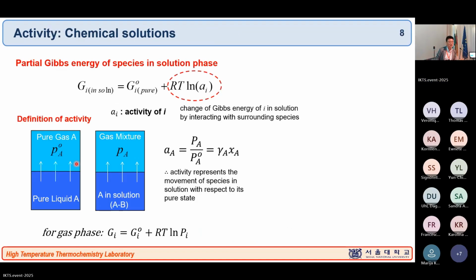Then what's the activity? So when you make a solution phase, because of the interaction between the species, the chemical activity, the movement of these species for chemical reaction, can be changed by your environment because of the interaction. And that's the activity we are talking about. Whenever you are looking at the solution phase, the Gibbs energy in the solution phase can be determined by the pure, standard Gibbs energy, plus a correction term. And that correction term is RT ln activity. Okay? And then the Gibbs energy of i in solution, we call it the partial Gibbs energy, because it's part of the solution, the partial Gibbs energy of i in the given solution.